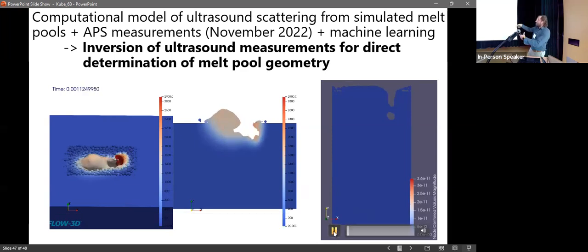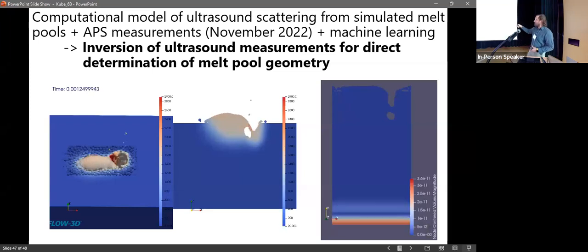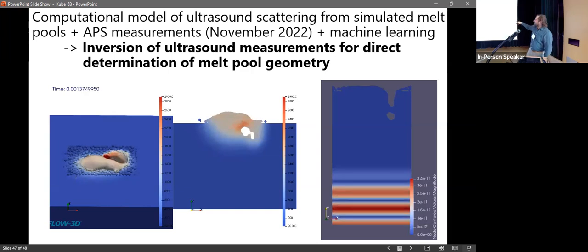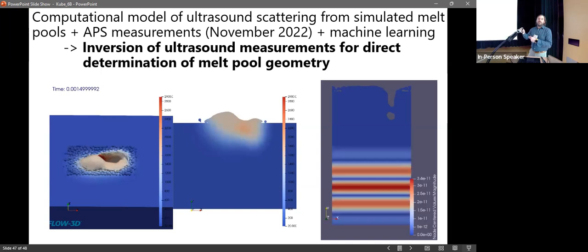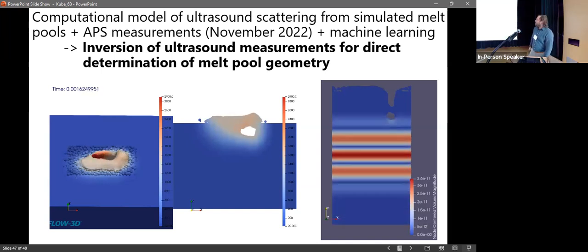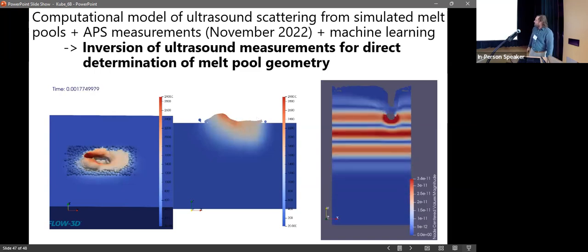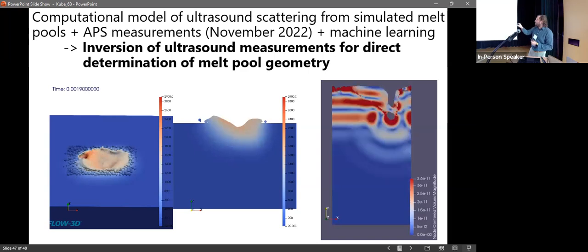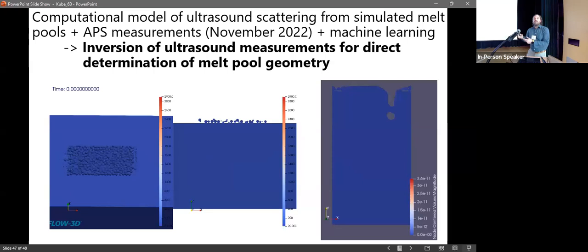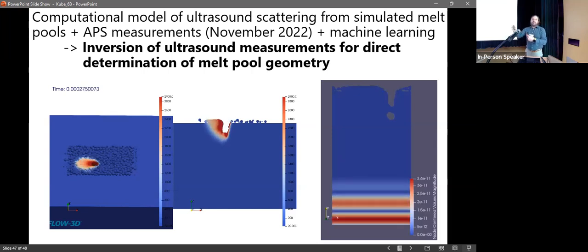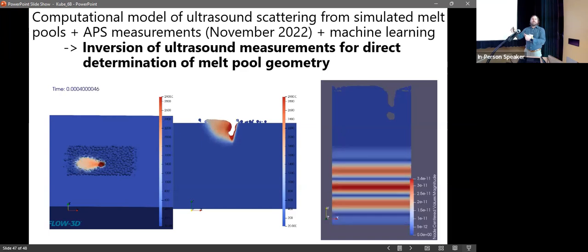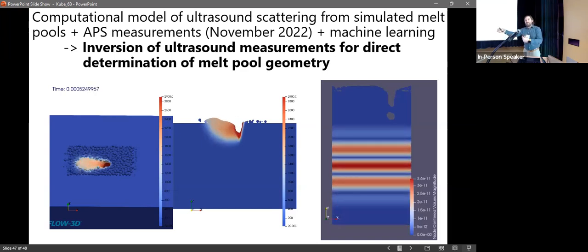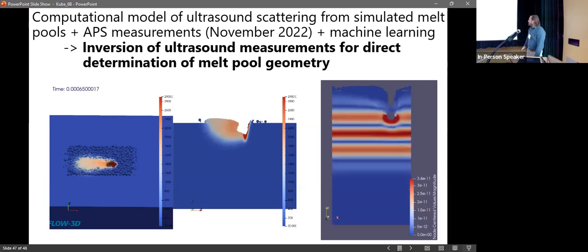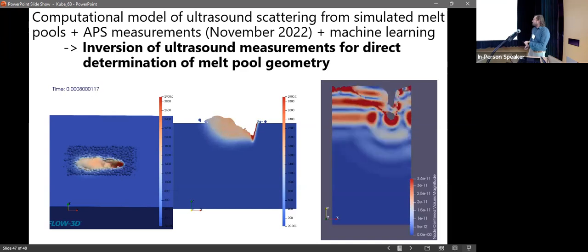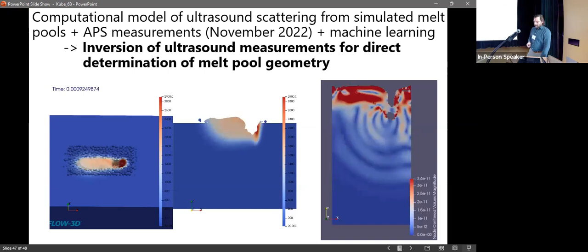And so on the right side, this is a frame taken out of the melt pool simulation where we're propagating ultrasound up into it, and we're going to get scattering from the solid liquid boundary and also the vapor liquid boundary here. There's also an interesting effect right where you expect the melt pool boundary to be. We get ultrasound to localize in those positions. And you think about that, you have a gradient in your stiffness and density in that region as your solid is phase transitioning into your liquid phase. So we're interested in the future to explore this a little bit more in our next set of measurements at APS.